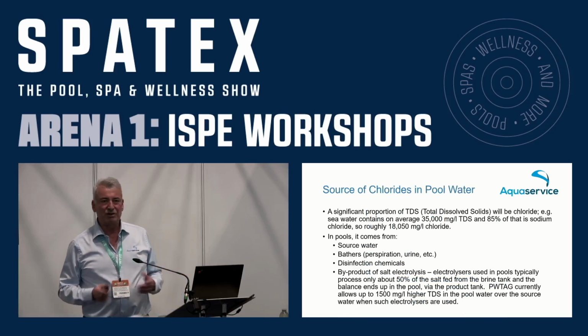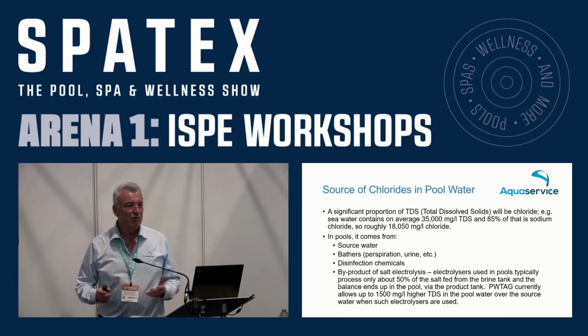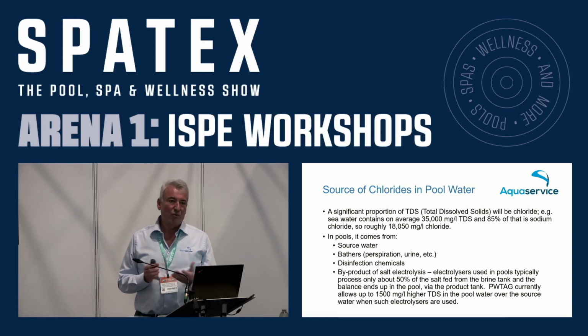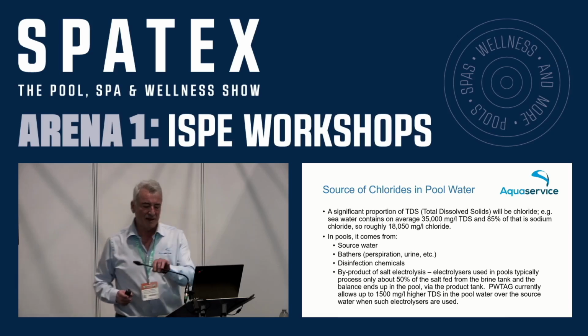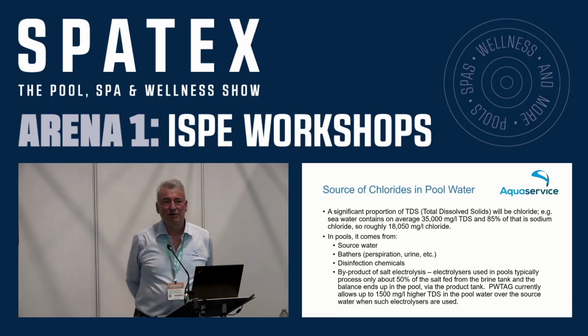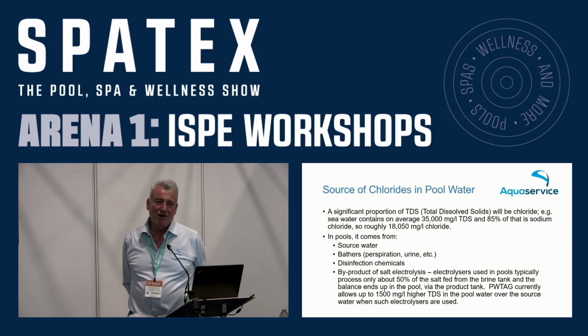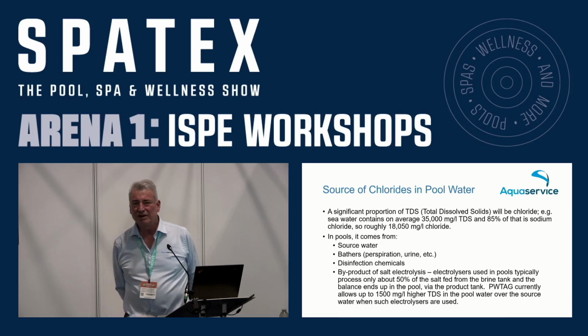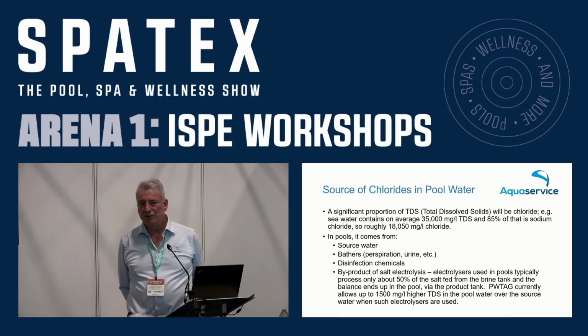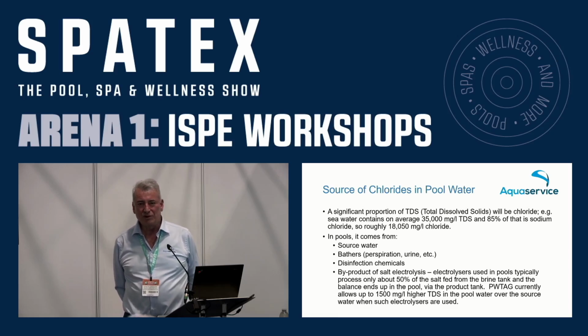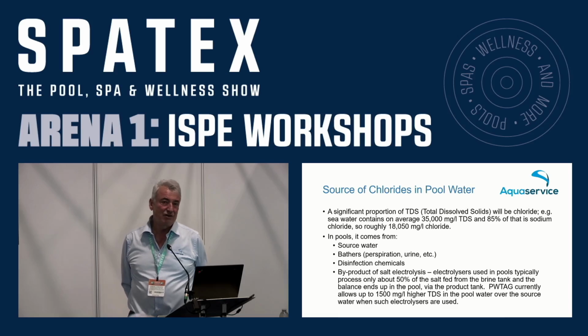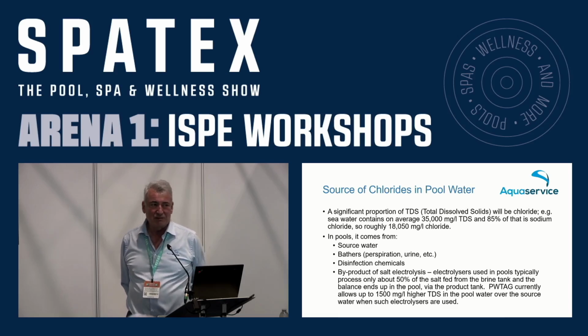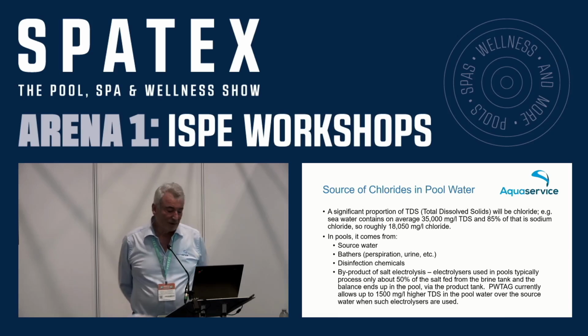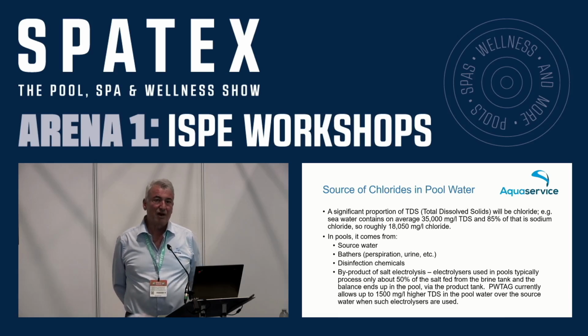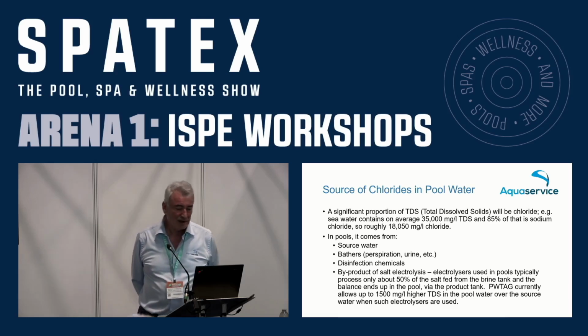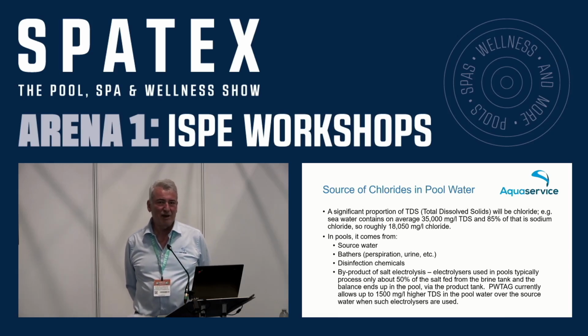Now, the sources of chloride are somewhat multiple. One source is the source water, and as an example, I have had experience in the past of this phenomenon occurring in Western Australia, where the pool source water was borehole water, which was brackish, and had a concentration of chlorides in excess of 2,000 milligrams per litre. So that's an example of source water. We don't get that sort of issue in the UK, fortunately, but it will come with its own incoming TDS load.